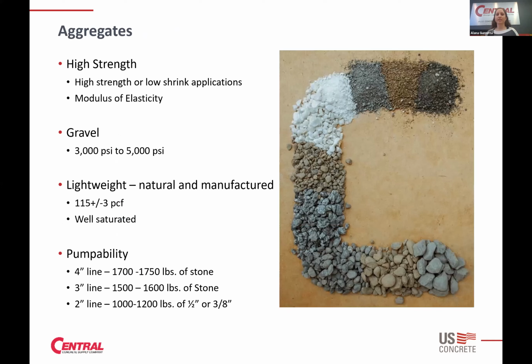There are a variety of different aggregates available and a variety of different reasons you would choose them. You can have high strength aggregates or high performing aggregates, which means you're able to achieve higher strength concrete, lower shrinkage, which is important as a piece of helping to mitigate cracking potential. And then also have a higher modulus of elasticity or a higher stiffness of the concrete. Your typical standard gravel aggregates, local to our area, we're going to be achieving 3,000 to 5,000 PSI concrete with that and going to the higher strength aggregates for anything above.